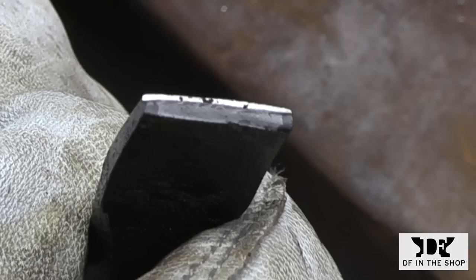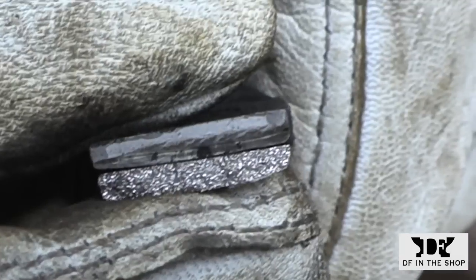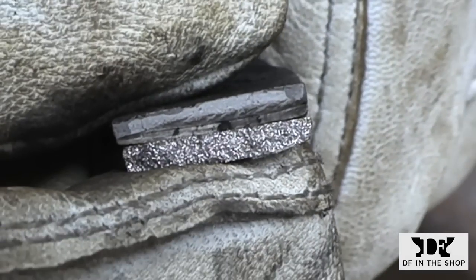And then I brought it back up to the critical temperature and quenched it in water so I could break off the edge and show you the difference in the grain. So this is the proper grain structure here. The shiny edge on the top is where I used an angle grinder to create a fracture point so I could break off the end of the chisel and show you a clean line of the grain structure. And here are the two grain samples together, and you can really get a clear picture of how different the grain structures are.